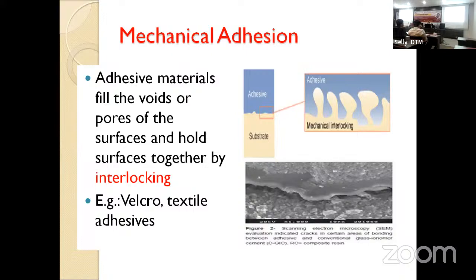In mechanical adhesion, you can see the adhesive and the substrate. The adhesive material fills all the voids and pores of the surface, and it will hold the surfaces together, and you can see interlocking. Look at that. It's a photograph from the scanning electron microscope, SEM. It's a composite resin, so it indicates a crack in a certain area. It's the bonding between the adherend and the glass. It's mechanical adhesion.